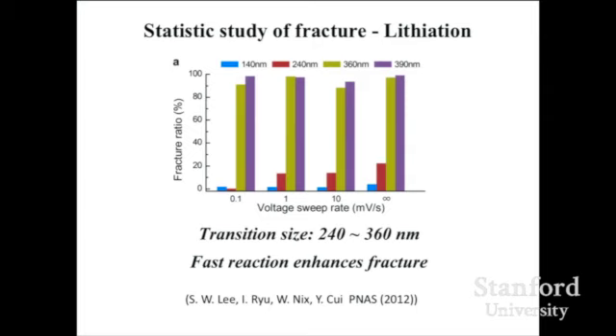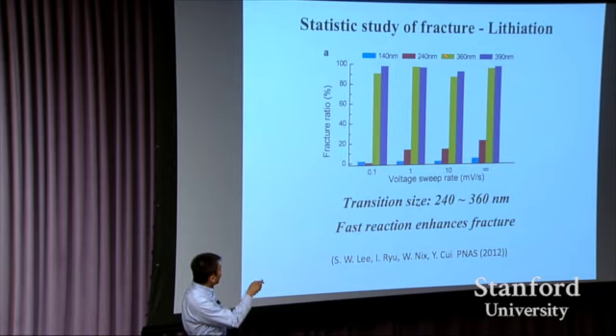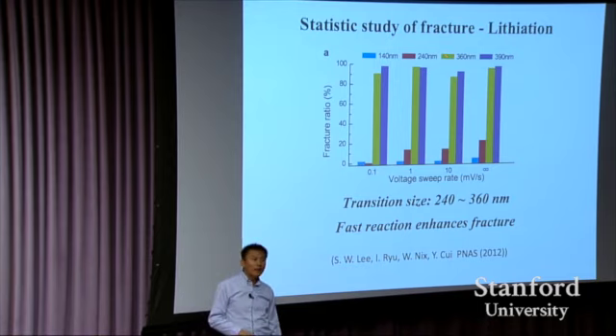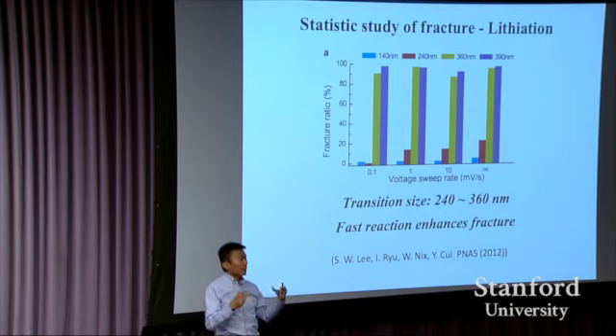And then you can also use different charging speeds to charge your batteries. The faster you charge, even for the 240 nanometer, the breaking ratio increases. Now the thinking is, I want my battery to be charged very, very fast. Can I do that? The answer is probably not. If you do it faster, you break your battery's materials. So if you want 8 minutes, 10 minutes of charging for electric cars, don't try that. You will probably break your batteries.